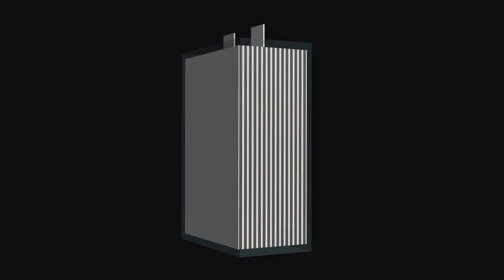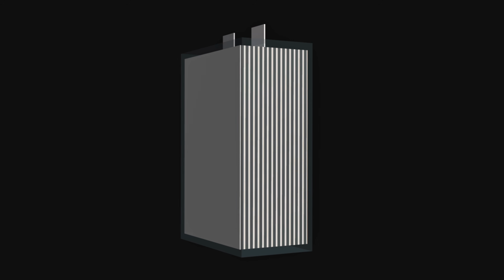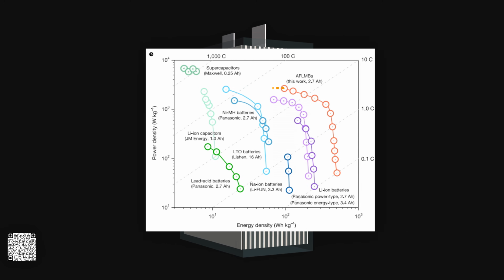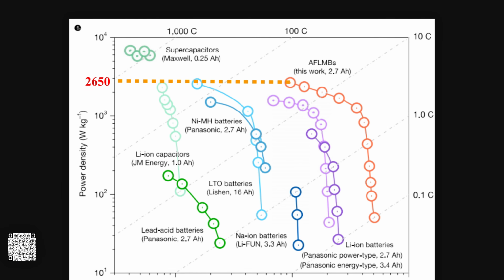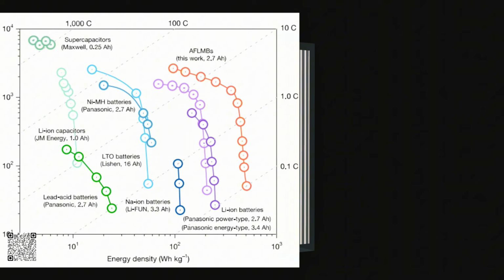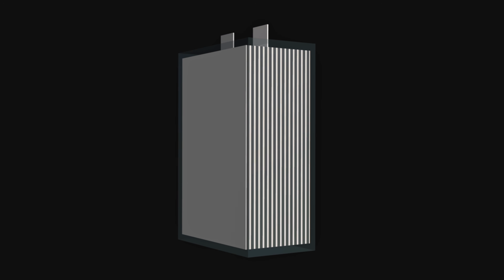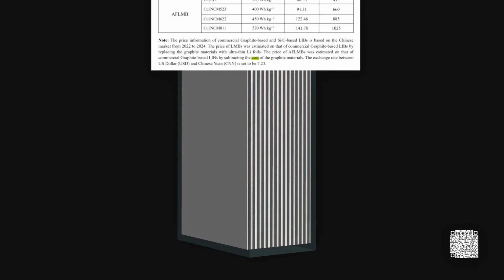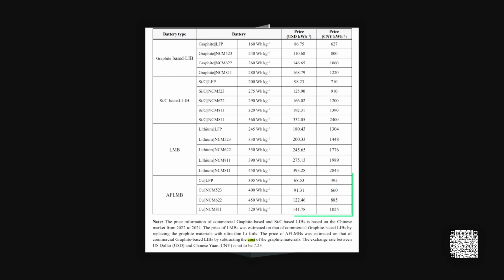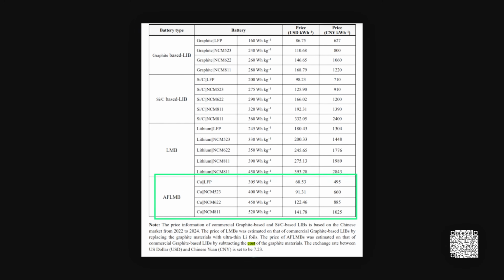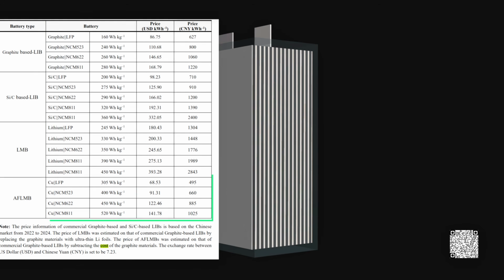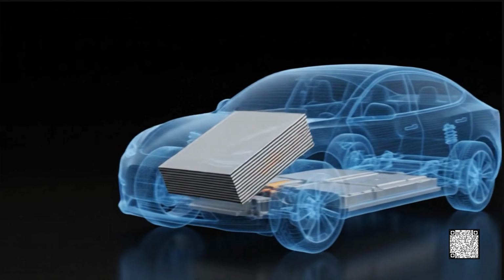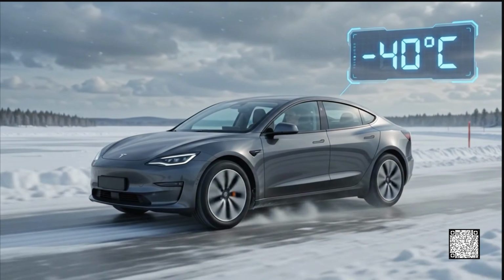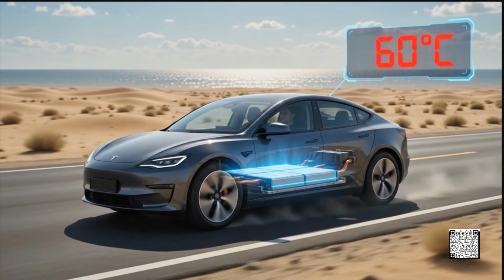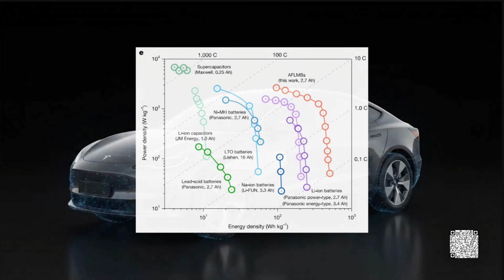1,668 watt-hours per liter, more than double a standard lithium-ion battery. It even pumps out 2,650 watts per kilogram of power. By eliminating the anode and reaching 100% capacity utilization, we're looking at a 15 to 25% reduction in cost per kilowatt hour. We've proved this works from negative 40 degrees Celsius all the way up to 60 degrees Celsius, and it handles discharge rates up to 7C.